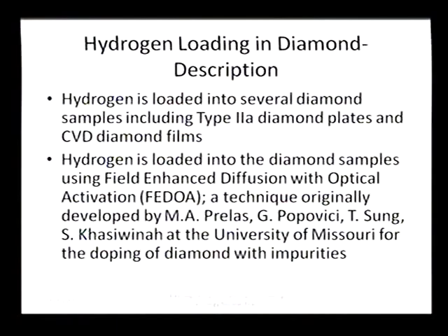We have been doing diamond loading or hydrogen loading experiments in diamonds since the early 90s. The idea started out as a means of understanding the semiconductor properties of CVD diamond, which had a very large hydrogen concentration in it. But we found that diamond in the CVD phase was able to store quite a bit of hydrogen, and so we began looking at what those limitations were for diamond. We use a technique called field-enhanced diffusion with optical activation.